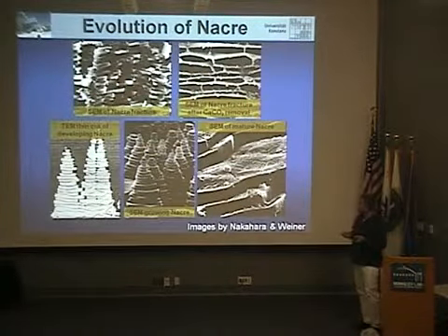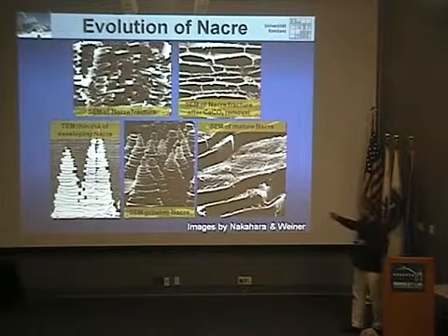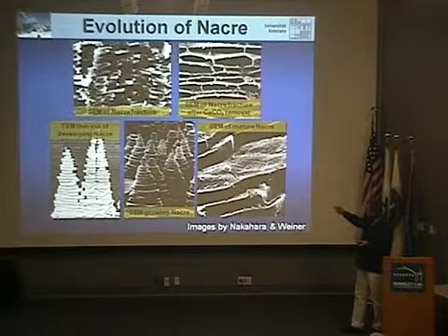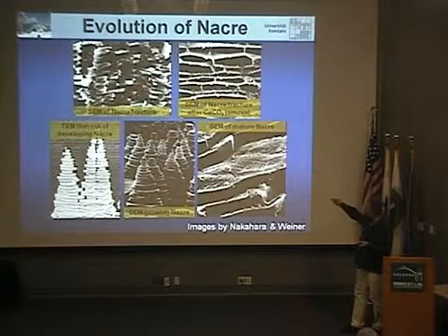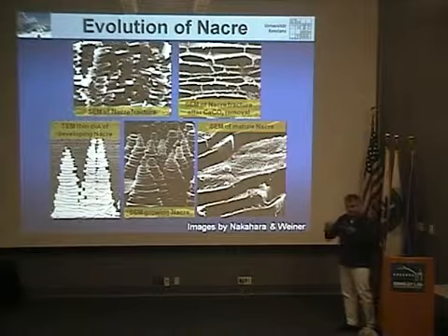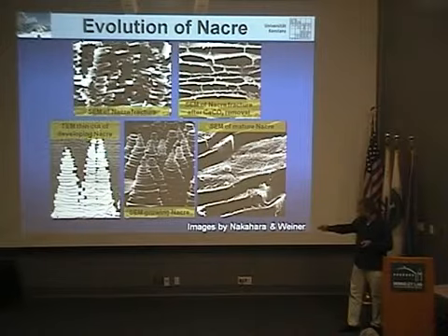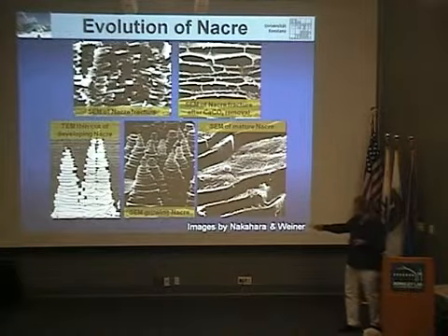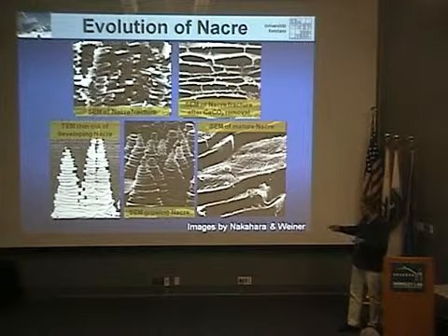And the reason why it's such a nice material is because it's layered. So you have calcium carbonate tablets in the form of aragonite, and they are fully surrounded by organic layers. So you have, if you dissolve out the calcium carbonate, you have these organic layers made out of chitins covered by proteins, and you have these bridges in between the layers. So every hard tablet is fully covered by the organic layers. And if you look at developing nacre, you see that first the cells secrete these layers, and we now know that they are filled with a silk hydrogel, and then the calcium carbonate tablets start to grow there, and then later on meet and form this material.